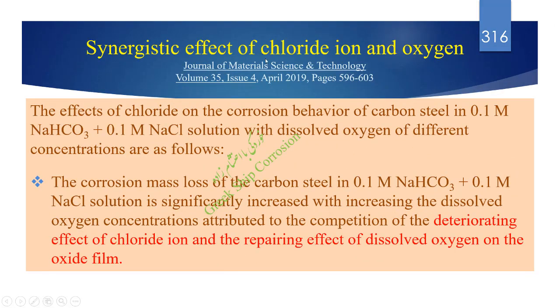Synergistic effect of chloride ion and oxygen. The effects of chloride on the corrosion behavior of carbon steel in 1/10 molar sodium bicarbonate plus 1/10 molar sodium chloride solution with dissolved oxygen of different concentrations are as follows. The corrosion mass loss of the carbon steel in this solution significantly increased with increasing dissolved oxygen concentrations, attributed to the competition of the deteriorating effect of chloride ion and the repairing effect of dissolved oxygen on the oxide film.